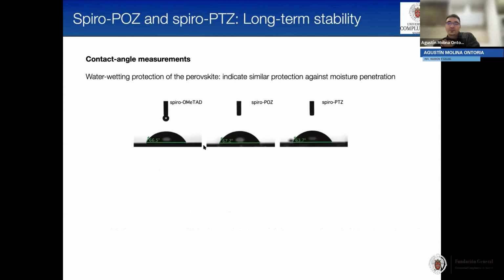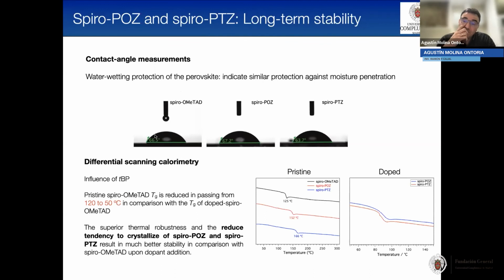So why were these molecules more stable than Spiro-OMeTAD? We first see the contact angle measurements to see how our materials protect the perovskite against moisture. And as you can see from the contact angle, we can see more or less the same angle. So they are defending the perovskite more or less the same. So why is the difference?